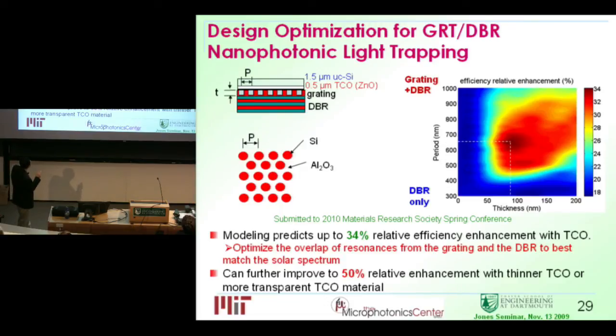It turns out this material still has quite a bit of absorption loss. So especially when light is diffracted sideways, the effective thickness that the light travels in this TCO layer also increases. So you get more loss from this TCO layer. So if we can improve on this, we can eventually get 50% enhancement.